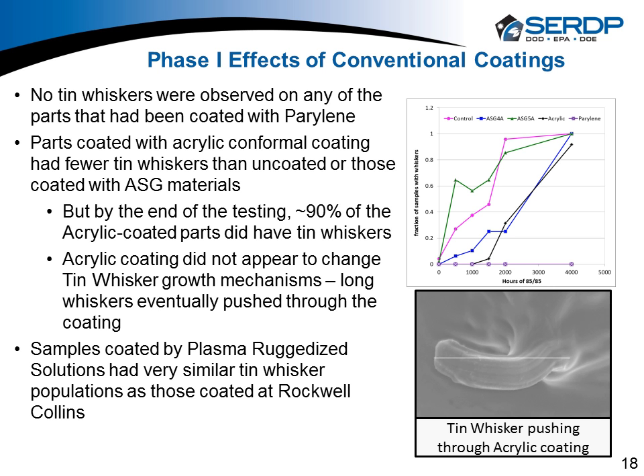I think what was more encouraging was the samples coated by plasma ruggedized solutions had the same behavior as the samples that we coated here at Rockwell. So someone using the same machine but a different facility, different state, completely away, independent coater of sorts, we ended up in the same place.